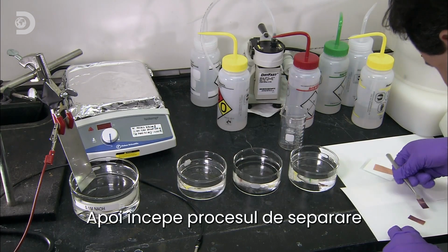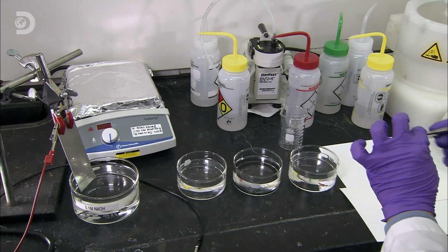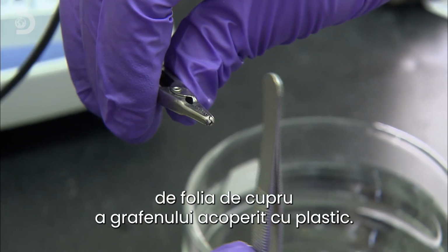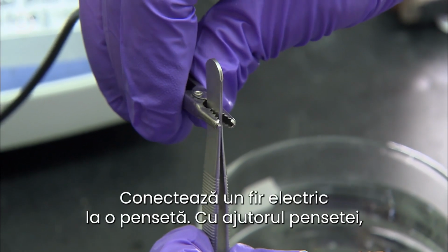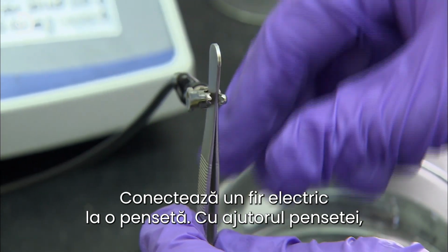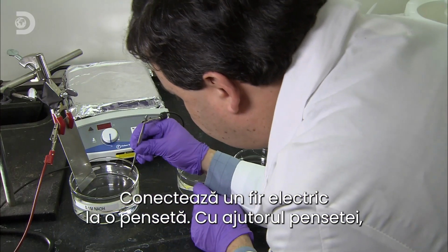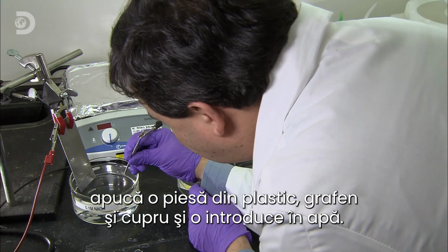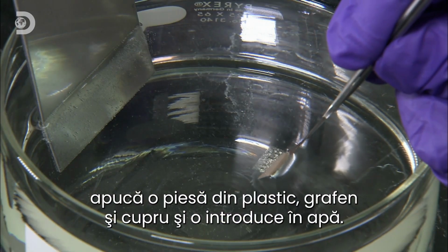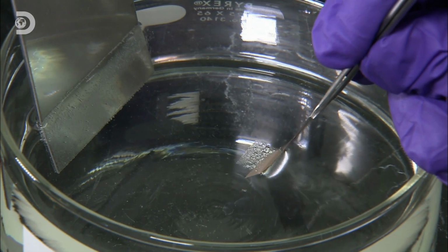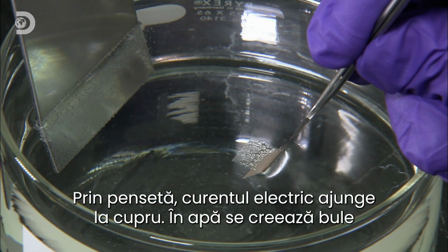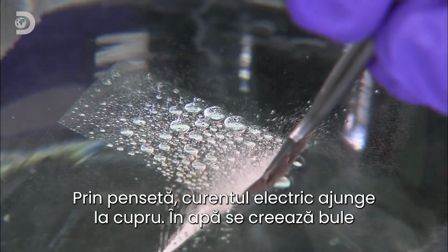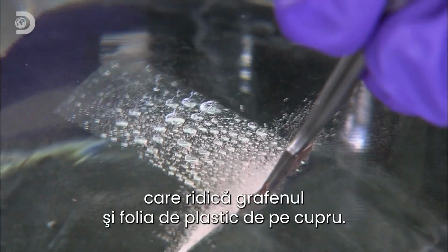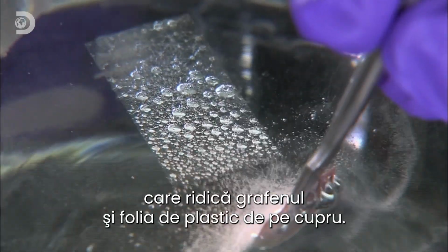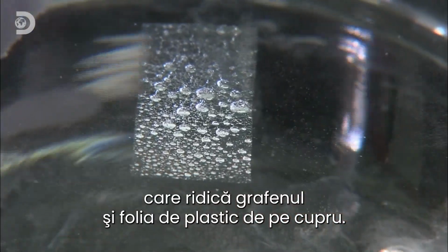Then, the process of separating the plastic-coated graphene from the copper foil begins. He clips a wire to a set of tweezers. Using the tweezers, he picks up a small piece of the plastic graphene and copper sandwich and plunges it into water. The tweezers apply an electrical charge through the copper. This causes bubbles to form in the water. These bubbles lift the graphene and plastic film away from the copper.